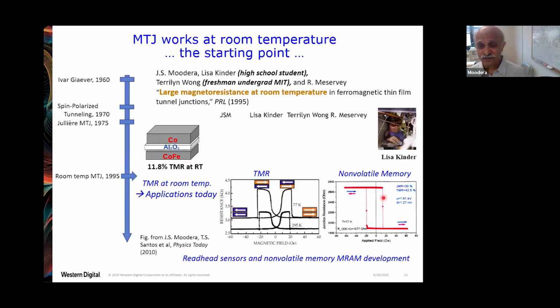At the same time, we also found that if you fix one of the magnetizations, it doesn't change very easily. But in this case, you see one of them changes here, the other one changes here. So both can be changed depending on the applied magnetic field. Now we fixed one of them, and we found that by toggling the second magnetization, going from parallel to anti-parallel state, you can have this kind of box-like structure. So what you have here is a zero magnetic field. If you go to high field, come back to zero field, you have a low resistance state maintained. Now you go in the reverse direction, make them anti-parallel, the resistance is high now. You just turn off the magnetic field, you actually reach this point.